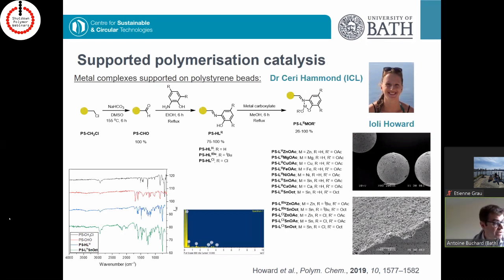So the way we approached this challenge of replacing those tin-based catalysts for industry was to go towards heterogeneous catalysis. And we went this way because there have been a lot of avenues exploring replacing tin with more abundant, more benign metals, and also some people looking at organocatalysis as an alternative to those metal-based catalysts. And the reason why people are interested in replacing those tin-based catalysts is because, even if those catalysts are approved, there is still increasing concern about the toxicity and also the effect that any residual catalyst will have on the polymer properties.